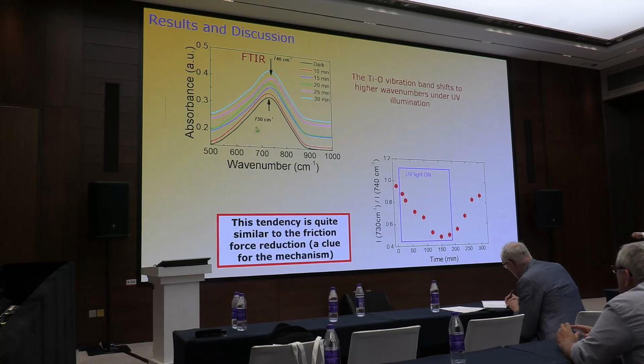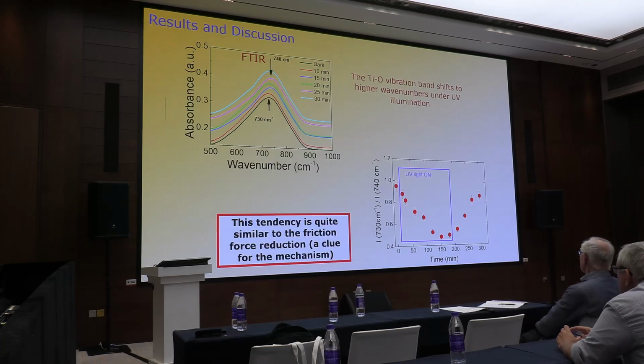Okay, and we plot two different curves here, the deconvolution of all this peak, and we divide the intensity of 730 by the 740. When the UV light is on, you can see that it decreases, and then when it's turned off, it increases again. There is a change of the vibration. We have different vibration. In other terms, when the system absorbs light, you modify the vibration of the titanium and oxygen on the surface. This is the result.